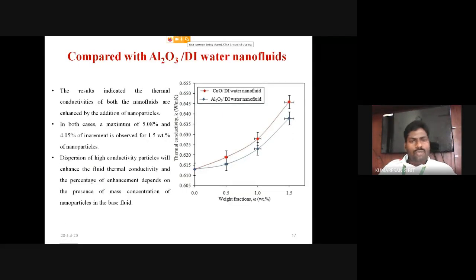Okay. In the comparison of copper oxide nanofluid thermal conductivity with Al2O3 DI water nanofluid, the results indicated that the thermal conductivity of both nanofluids is enhanced by the addition of nanoparticles. So irrespective of the particles, aluminum oxide and copper oxide, both nanoparticles increase the thermal conductivity value.